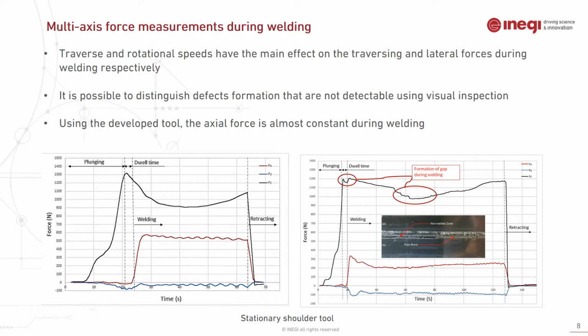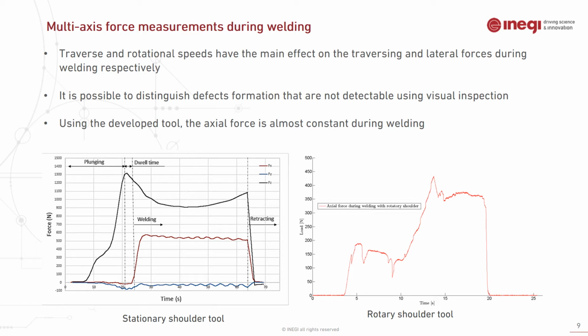process. It was concluded that the traverse and rotational speeds have the main effect on the traversing and lateral forces during the welding. Also, it was possible to distinguish defect formation that is not detectable using visual inspection, as you can see in the right image, and this step created in the axial force was related to the formation of a gap during the welding. Also, using the developed tool, which is a stationary tool, the axial force is almost constant during the welding. And as you can see here, the difference between the stationary shoulder tool and rotating shoulder regarding the axial force.